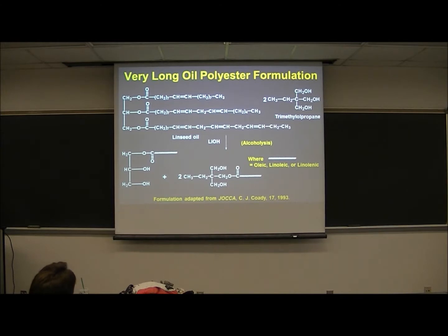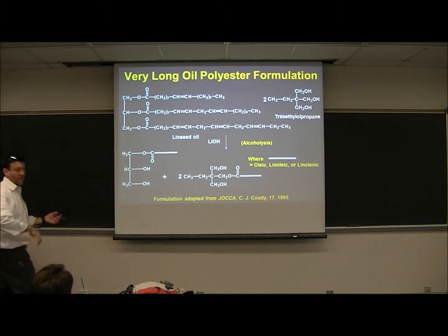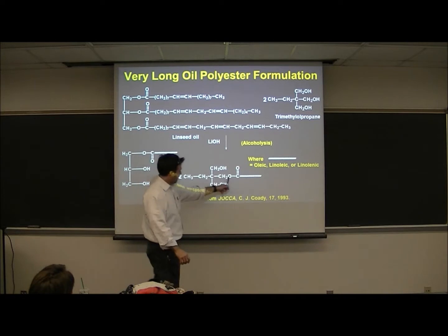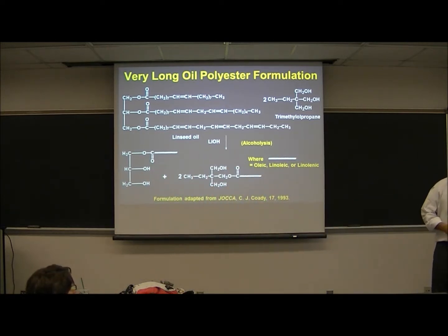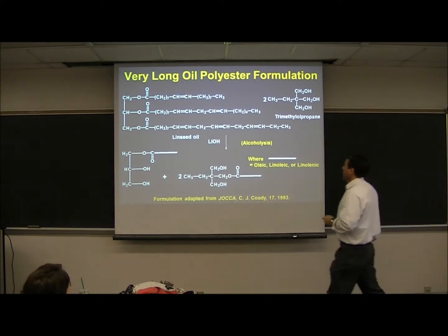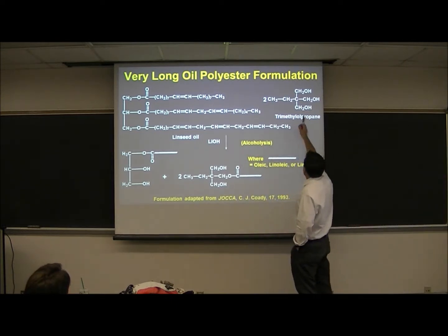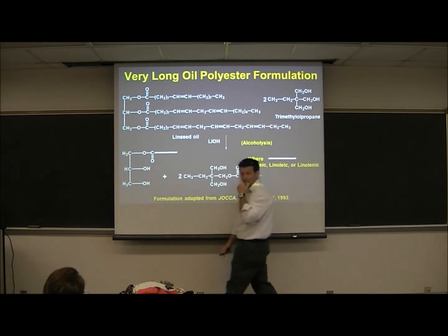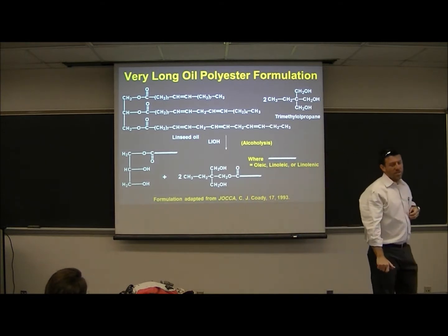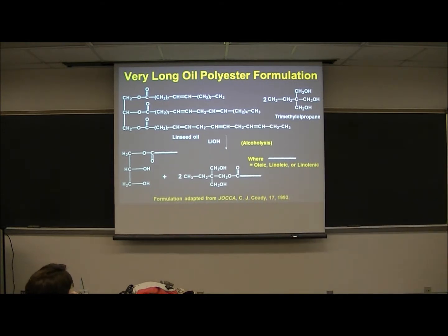IR will not be definitive. IR will tell you that you have the same range of hydroxyls before and after. It'll tell you they have the same range of esters, but it won't define that that ester is any different than that ester. What about molecular weight? Will that be different? Well, you're going from what should be about 878 plus whatever that is, and now you've rearranged it across different molecules. Your molecular weight average is changing slightly, but you have to keep in mind, from top to bottom, it's not changing.